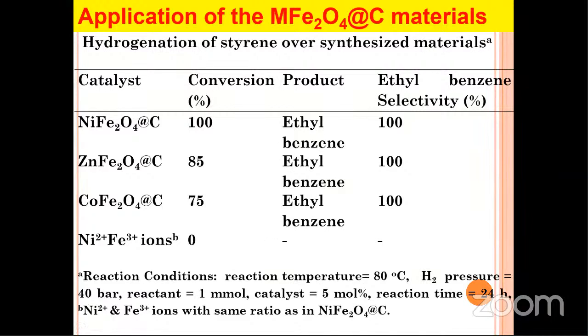The prepared material was used for a hydrogenation reaction. Most of you know that nickel, zinc, and cobalt act as catalysts for hydrogenation reactions. So I tried this material for the hydrogenation of styrene. We get 100% conversion in the case of NiFe2O4 on carbon. We see that this special combination of NiFe2O4 on carbon gives 100% conversion.